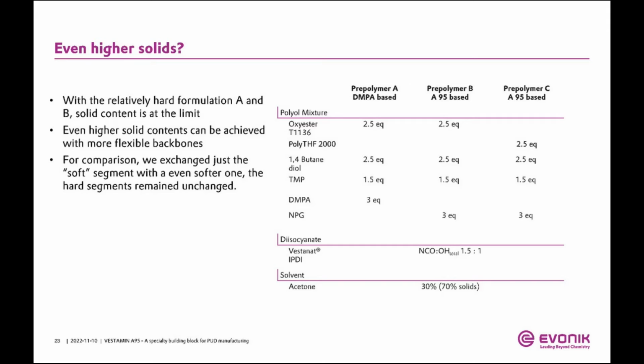you just increase the amount of flexible backbones. So in this case, we go for a poly THF with a 2000 grams per mole molecular weight, and exchange the polyester we used before in the first examples. We now choose this poly THF 2000. So you see this in the table, right? You have now a pre-polymer C, which is again in most of the properties unchanged, except that the polyester is not used anymore. Now we use a doubled molecular weight poly THF based. For the rest, we did not change anything again.